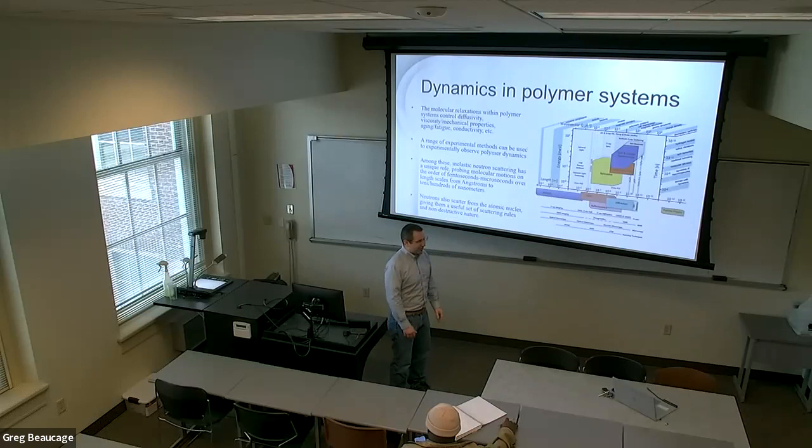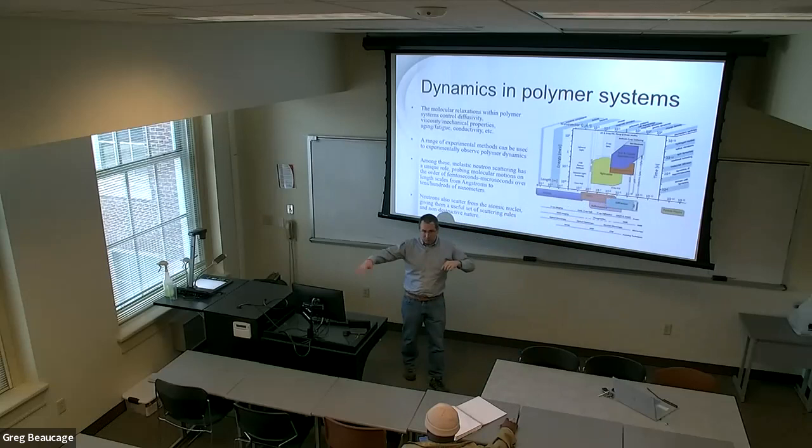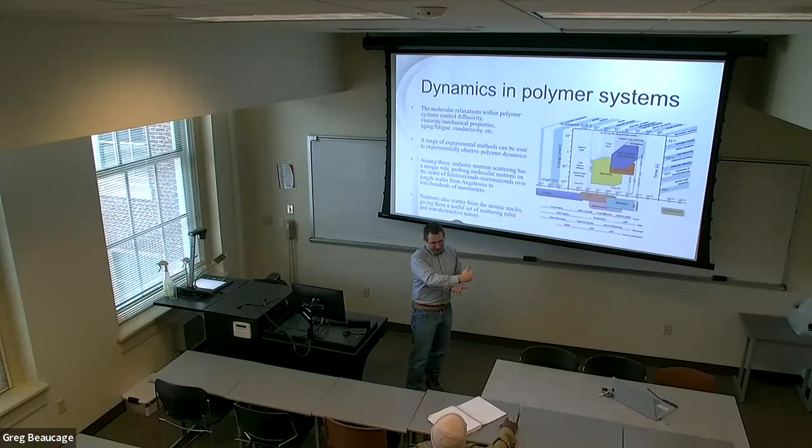Yes, because there are some practicalities for these experiments that we should talk about, which is that they take a long time. Typically a backscattering measurement that I'm making, like the ones for the paper I'll talk about here, were probably 4-hour collections. Now, in the case where you just have a piece of polymer that's not doing anything, just sitting at a certain temperature at a certain hydration content in a sealed container, that's okay, right? You're looking at steady state self-diffusion, fine. If the system is being probed and you're purporting to represent that in the data, are you really representing that through the whole time course of your collection? Probably not. So you have to be careful with that. You should at least discuss it.